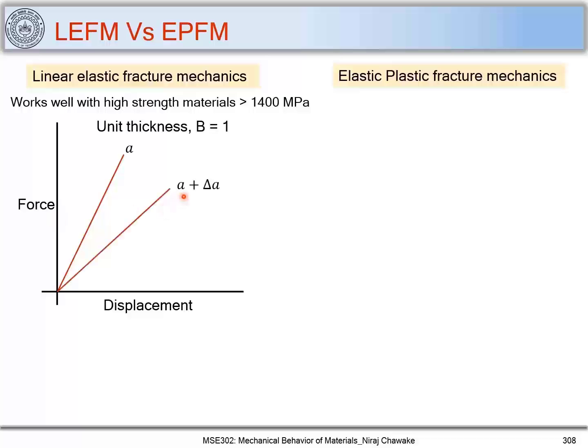Now let's say you have a crack A plus delta A, a small increment in the crack length. And we have seen that the force to extend such a crack, which is slightly bigger than this crack, will require a smaller amount of force. The energy which we get in between, we term it as G dA. We have seen this. So the difference between these two will give you the quantity G dA. dA is nothing but a small increment in the crack, and G is the strain energy release rate.